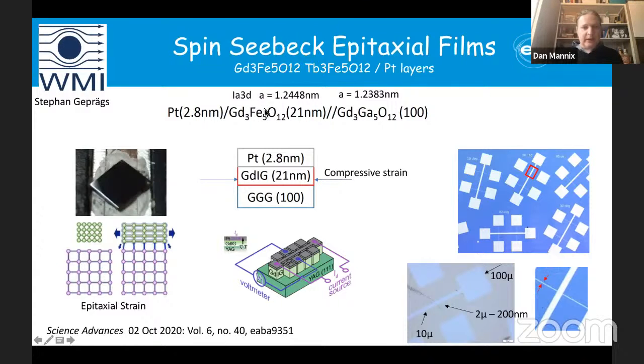So there's a gadolinium iron garnet, Gd3Fe5O12, at about 20 nanometers thickness. And on top of that, we grow the platinum that I've described as part of the spin-Seebeck effect composite. But these materials are epitaxial. They will have epitaxial strain. So there's a strain which is given by the mismatch of lattices in the substrate, and that can be important also in tuning properties inside these materials. Strain is known to go inside the band structure and affect many functionalities, not least magnetism too, and magnetic domains. So this is an important aspect in our materials.